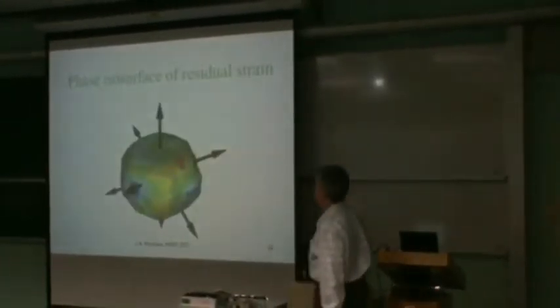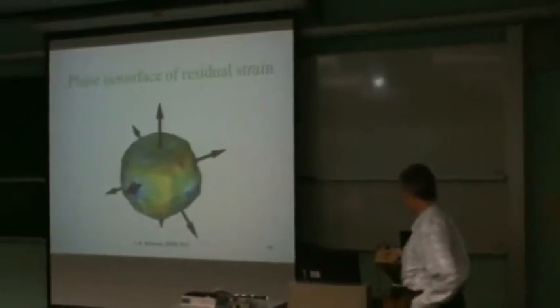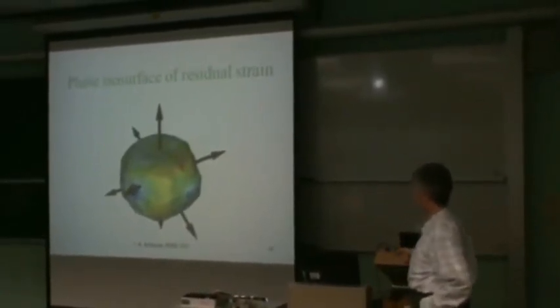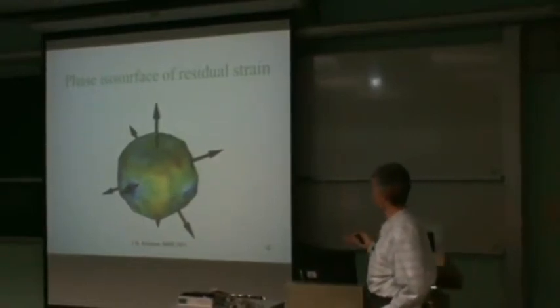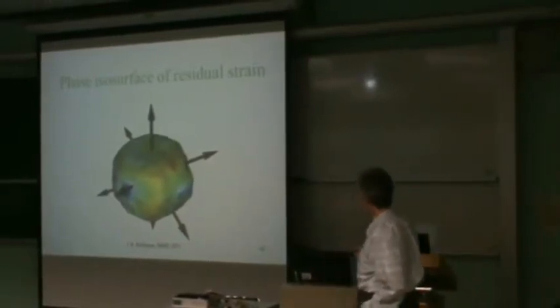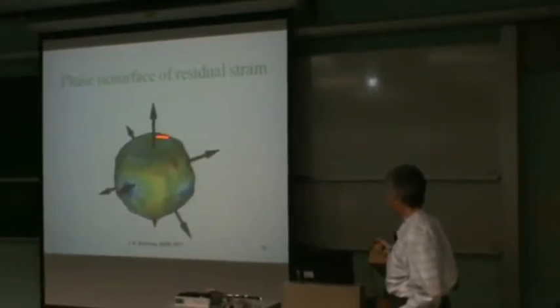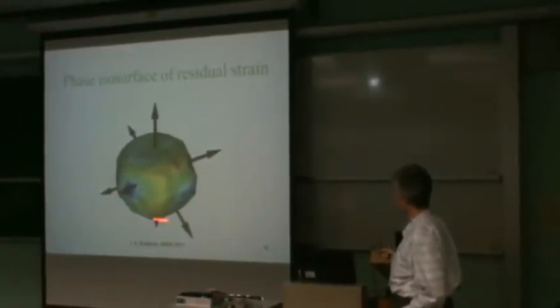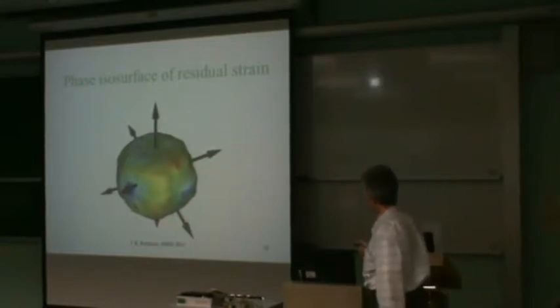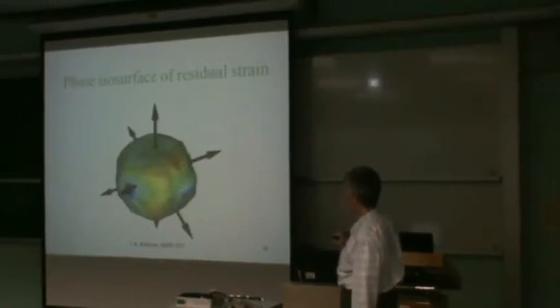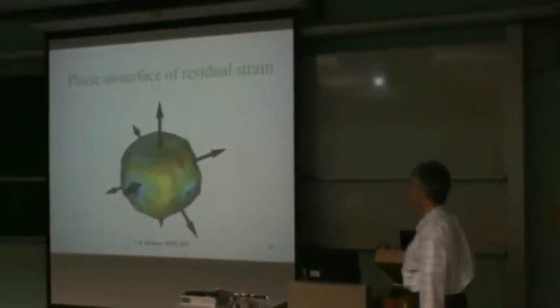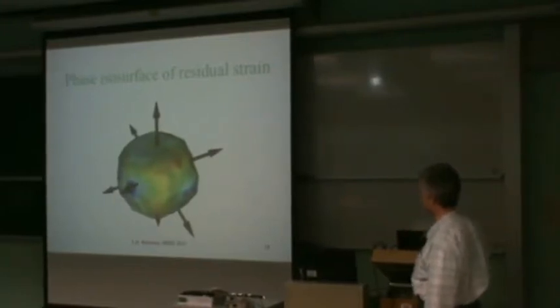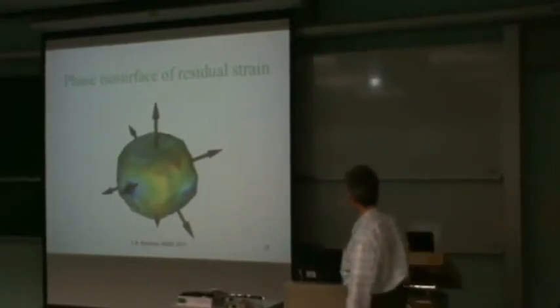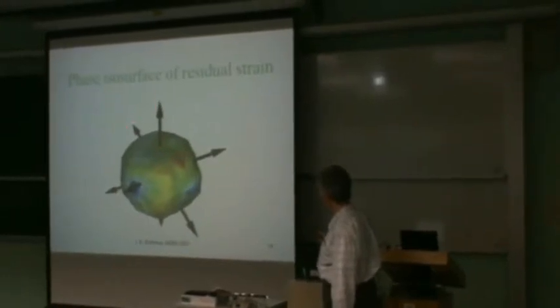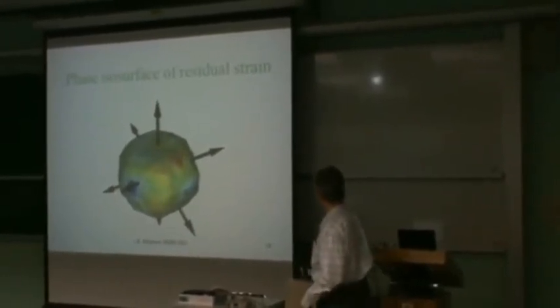And here's where the phase information appears. It's usually quite difficult to view because it's a three-dimensional complex density function. The most useful information is very often to look at the surface of the sample, so you just make an isosurface rendering of it, and then color the isosurface according to the phase of the complex density which is inside there. This is where the strain gets mapped onto the image. The arrows indicate the 111 directions of the facets of the crystal.